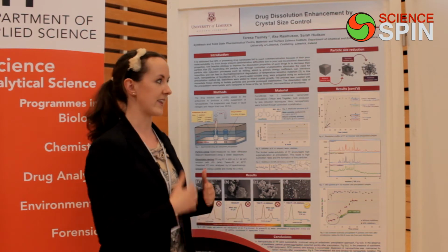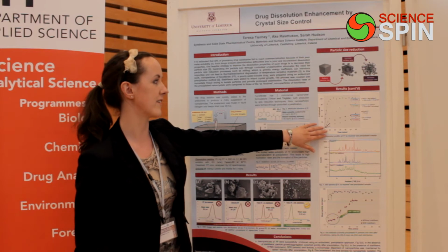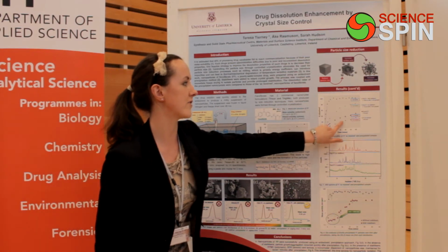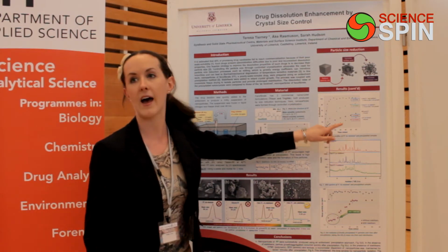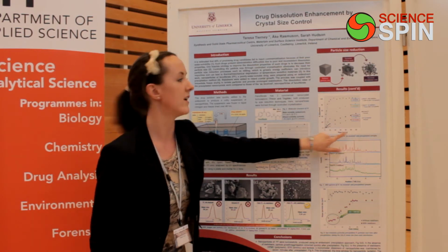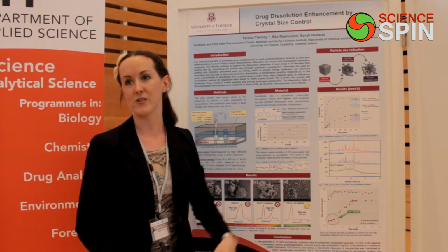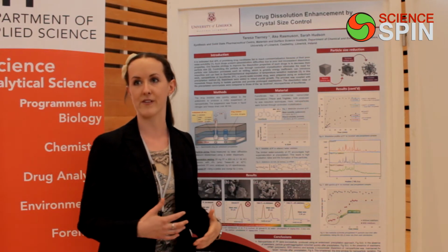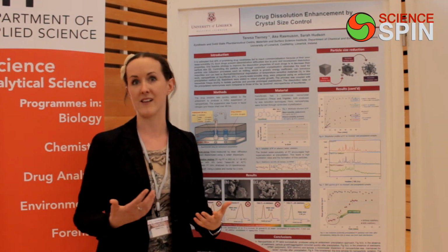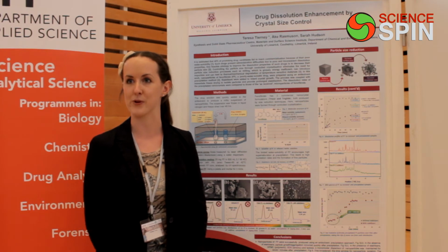Then I do some dissolution testing on those, as you can see in this graph. This is the dissolution rate enhancement compared to the as-received material. It's quite slow: it dissolves 20% in 1 hour, whereas my nanomaterial dissolves 100% in about 10 minutes. So it's quite a significant difference, and that would give enhanced dissolution rate and bioavailability in the body and lead to better drug performance, more or less.